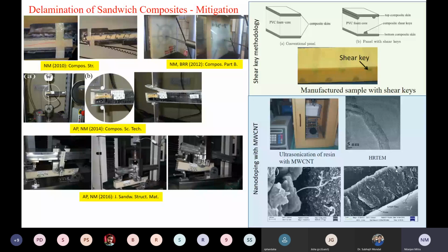So that's quite a common thing. So we devised some methodologies by which we can prevent this delamination. One of them is called a shear key. It is a ridge that you place within the foam, such that even if a crack initiates, that crack path will get deviated, right? So that's an application of a shear key.